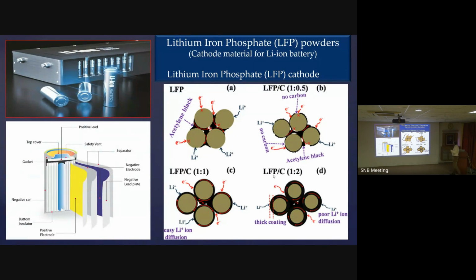But what is key in the process? Lithium iron phosphate is not a new material. If you take lithium carbonate, iron oxide and ammonium dihydrogen phosphate, you can make LFP. Anyone can make it. But what is important is that lithium iron phosphate is not electrically conducting, and it cannot be used as an electrode unless you have a carbon coating on it for current collection. So you have to have a uniform carbon coating, but as minimal as possible, because it will be dead weight for the electrode, right?